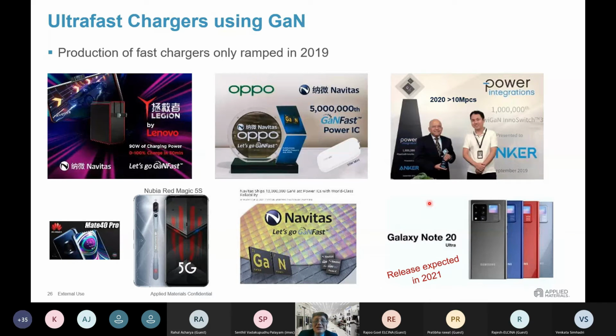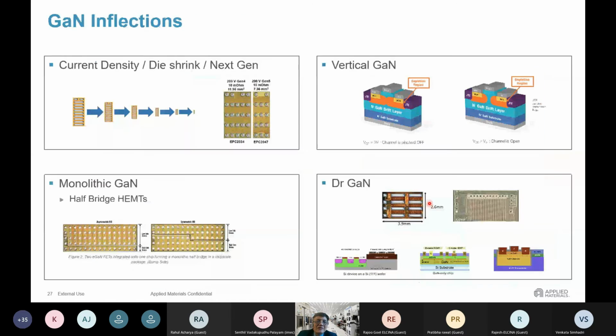In 2019-20 is the time when the gallium nitride-based mobile chargers have taken off in a big way, and it's actually creating a pull where the gallium nitride is creating volumes, and it's moving into the mainstream. Not quite where the silicon is, but clearly the inflections are visible. And this is the technology landscape that we see that could be there.